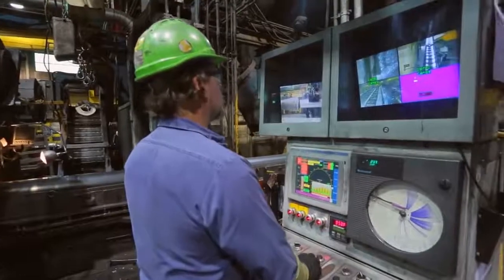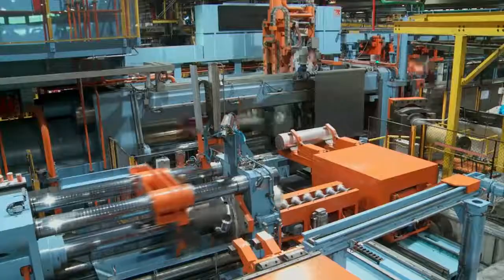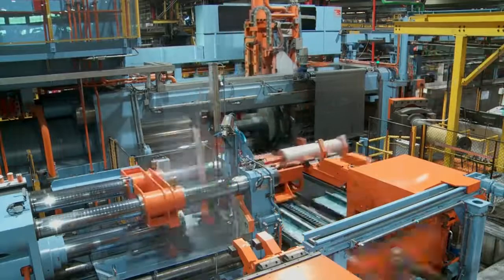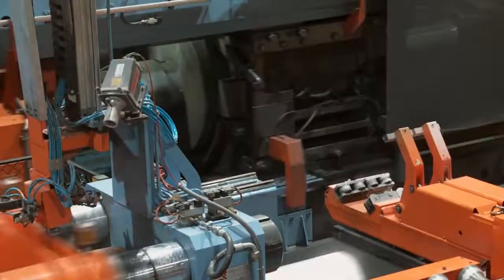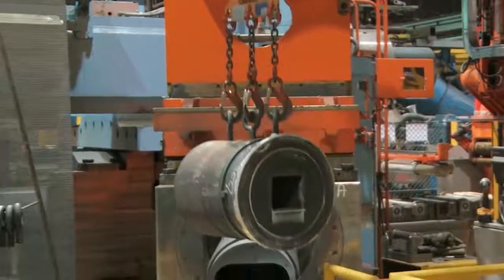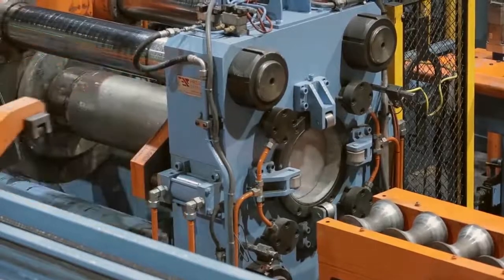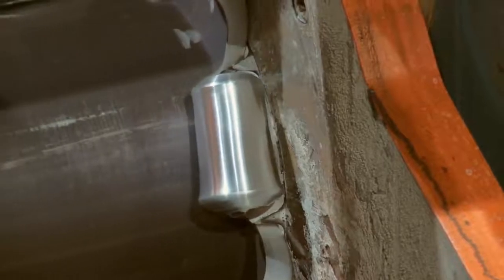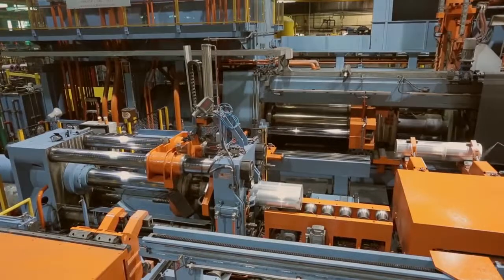There are several key differences between direct and indirect extrusion that make them valuable for different needs. Indirect extrusion requires less die face pressure, while it minimizes the friction and heat to allow for more consistent dimensions, properties, and grain size. There is a sacrifice of overall shape size, however, because the special tooling must fit inside the hollow ram. Since the outside of the billet becomes the outside of the extrusion, the billets must be scalped to remove the outer surface. Scalping removes a shaving of material from the outer diameter of the billet.